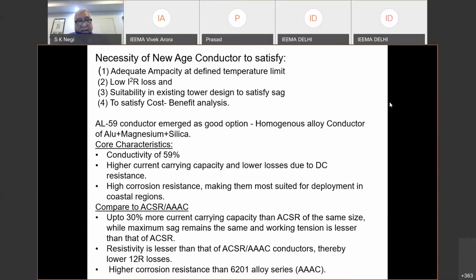Now, having said the characteristics of the AL59, when we compare with the ACSR Hormuz conductor, it carries 30% more current, and that too at a temperature of 95, while maximum temperature remains the same, and working tension is lesser than ACSR. So this is a very, very important factor which triggers the thinking process toward the AL59. Resistivity is lesser than that of ACSR and AAAC conductors, thereby lower I square R losses, and higher corrosion resistance, as I already said. So this is the background under which AL59 has an edge over the ACSR conductor.